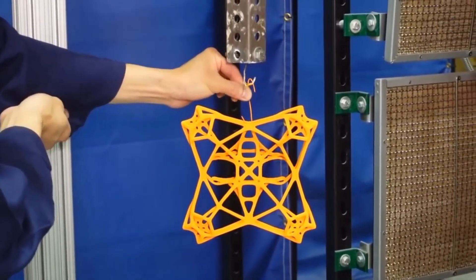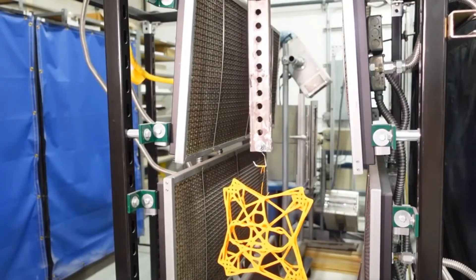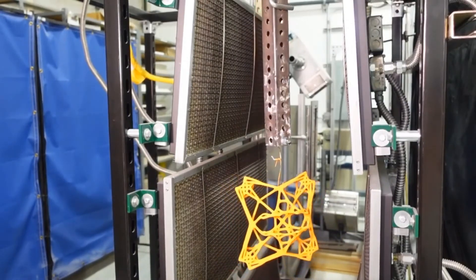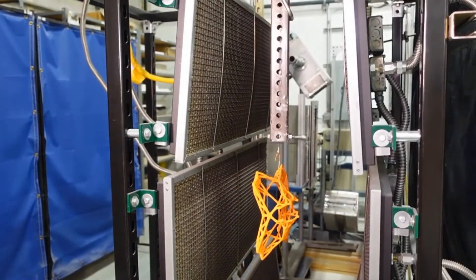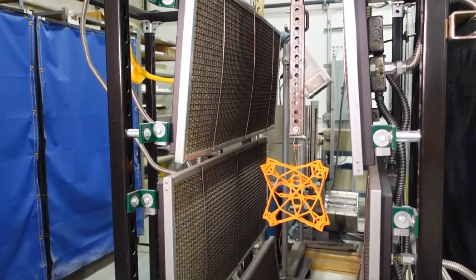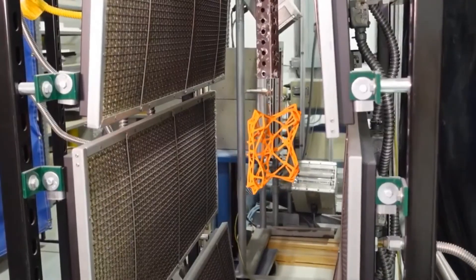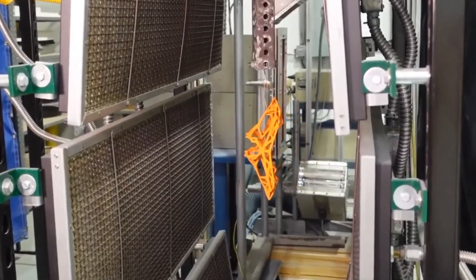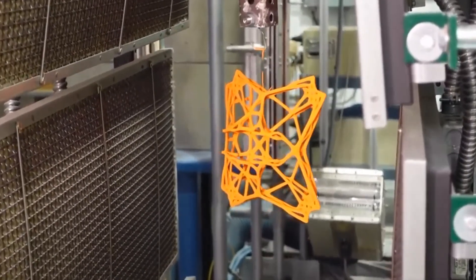The part is now hung on our UV lab line in our R&D facility. It moves down the conveyor stopping and rotating in front of an IR panel for a few minutes. This is called the melt flow stage in which the powder flows and levels to a high viscosity liquid state and becomes one uniform mass. Here the powder is subjected to high temperatures to enable the surface temperature to reach 120 degrees Celsius.